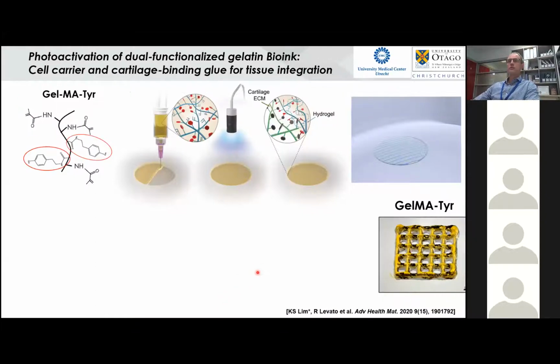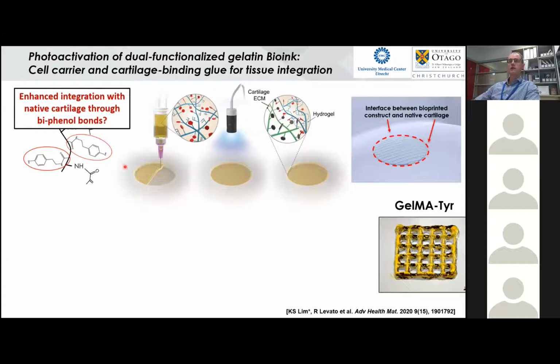One other example in terms of using similar types of technologies is that we don't necessarily have to only cross-link the hydrogel. We also have a number of tissues we're working with which potentially might take advantage of this dityrosine or biphenol cross-linking. This is just another example, if you're trying to see if you could print a hydrogel construct that could be printable, but then also bind with surrounding native tissue. This is just an example with essentially a GelMA tyramine.